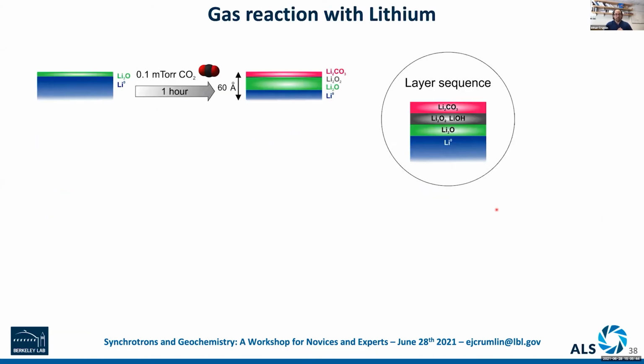I want to show one last example with regard to the solid gas interface interaction. And this is with how we can see reactions taking place. So not just surface adsorption or some small molecular changes, but large changes as well. So here we're going to take lithium, we're going to clean it very well, we're going to expose it to different gases. And so we've already done the analysis, and we're able to start to quantify the different types of chemical species and their relative locations to each other on the sample.